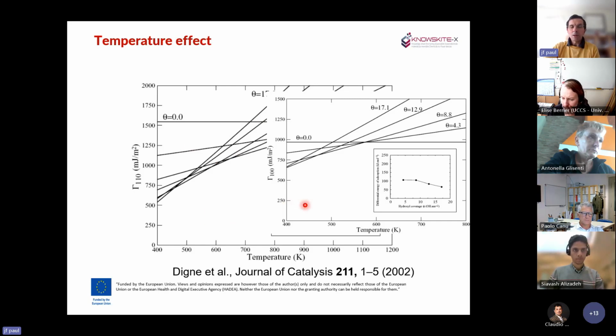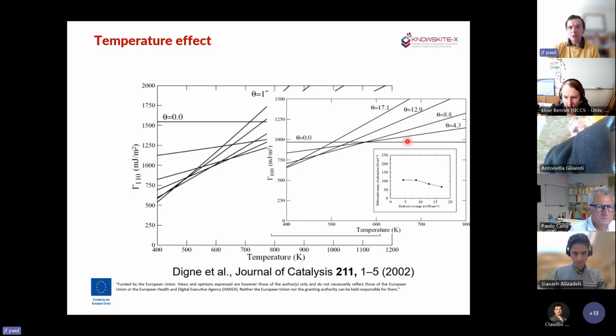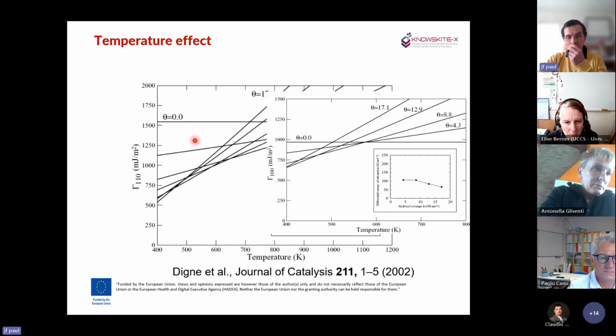And you can see here that when the temperature increases, the number of molecules adsorbed on the surface decreases a lot, and you go from something which is totally saturated to something which is completely bare without any water, going from 400 K to 600 K. So the evolution is quite rapid. And taking into account the effect of the environment, it's now possible to know how many molecules you have.